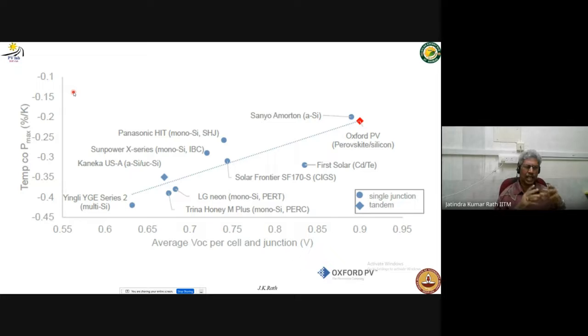The temperature coefficient means, let's say somebody says I have got a 20% efficient solar cell, but actually outside the efficiency will be lower, or the power will be less. That depends on the coefficient. Crystalline silicon typically is minus 0.45 percent per Kelvin. That means a lot of power will be lost in hot conditions. Let's say in India, where the outside temperature is 50 degrees and the cell temperature goes up to almost 80 degrees, you can see there will be a lot of power loss. For Indian conditions, you need very high voltage cells. So either you go to silicon heterojunction cells, which are quite high voltage, or you go to complete tandem cells like this. That will help to get a low temperature coefficient of the efficiency or power. So both things help, which is why we should go towards tandem cells.